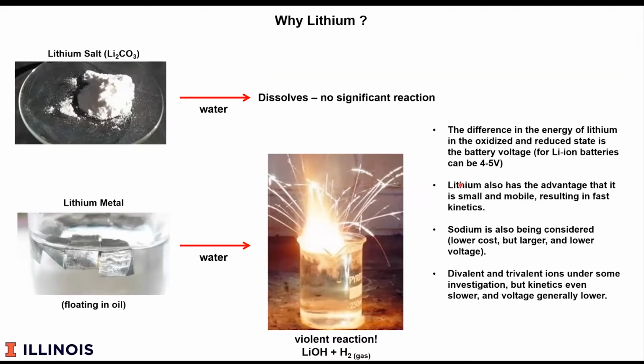So why is lithium interesting? Lithium is interesting because it's small or lightweight and it's highly mobile, and that results in fast kinetics. And it's also interesting because of the difference in the potential between its oxidized and reduced state. Sodium's also being considered. We've had some successes in creating sodium-ion electrodes. Sodium is interesting because it's lower cost, but it is larger and generally lower in voltage. And so it's unclear if sodium will have a real impact on transportation. It may have more of an impact in things like grid scale storage, where one is looking at storing and releasing the energy at much slower rates, and the mass and volume of the system becomes less important.